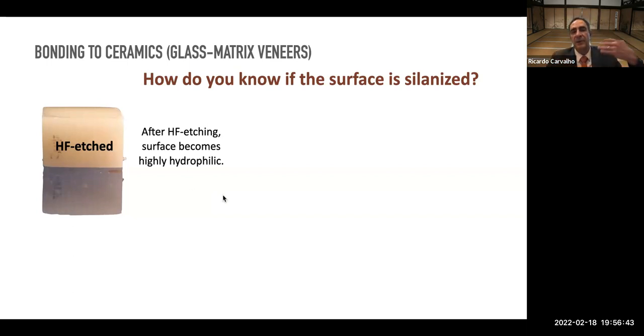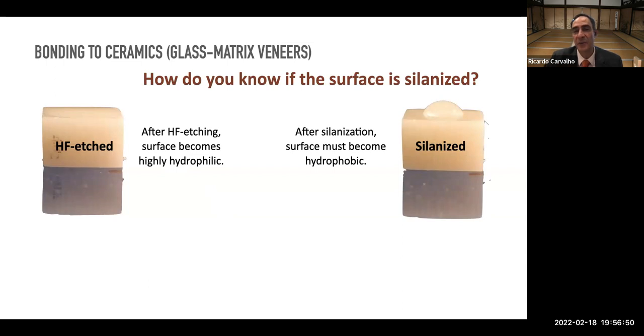And then I rinsed, I applied the silane, and after the silanization, the surface must become hydrophobic. So that's the difference. You can only see the chemistry that is changing on the surface. And after silanization, when I apply a drop of water, the water does not spread, indicating hydrophobicity on the surface and an indication that silanization actually occurred. And we can actually measure the contact angle of this drop on the surface, and we can somehow quantify how well the surface is silanized by utilizing the contact angle.